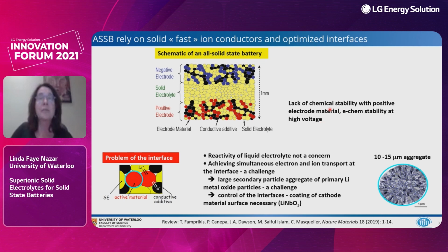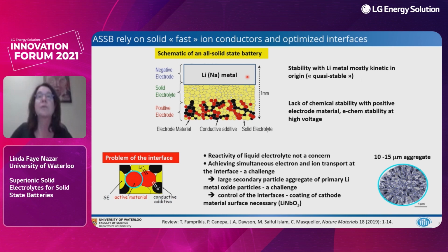So just to highlight the concerns here, we have lack of chemical stability of typical sulfide electrolytes with the positive electrode material, and poor electrochemical stability of those sulfide electrolytes. It is widely thought that lithium is probably going to be the negative electrode of choice, although we can't totally rule out sodium, and Shirley Meng has done some really lovely work, as others have, on silicon anodes. In general, one has to think about the stability with lithium metal being mostly kinetic in origin. In other words, it's quasi-stable. So in principle, one also needs to implement an artificial membrane next to the lithium metal to prevent that instability, or else to generate a passivating layer in situ that solves that problem.